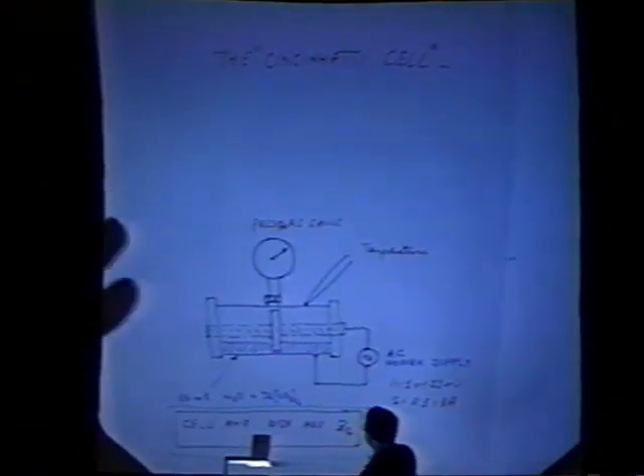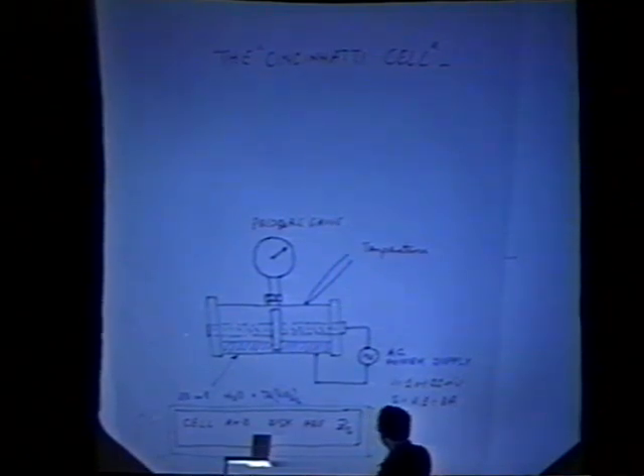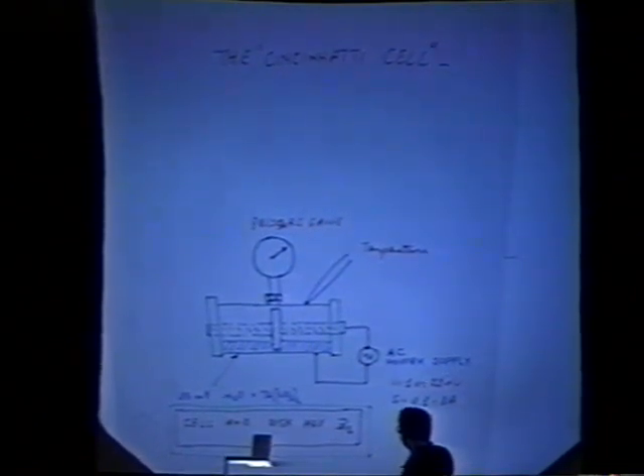A sketch of this cell is a zirconia cylinder with, at the center, a zirconia disc, where some AC voltage is applied, from maybe 10 volts to 220, and current as large as 8 amperes. The temperature of the system can increase abruptly to 200 Celsius. The pressure can increase abruptly because there is a positive feedback between the electrolyte conductivity and the voltage applied. So the temperature increases, the conductivity increases, so the pressure increases, and so on.